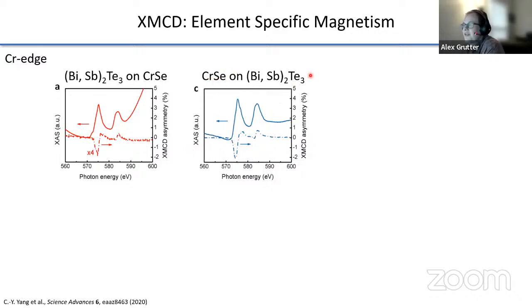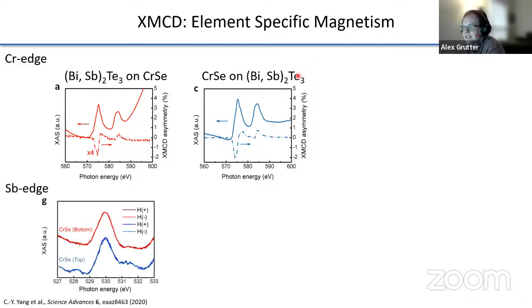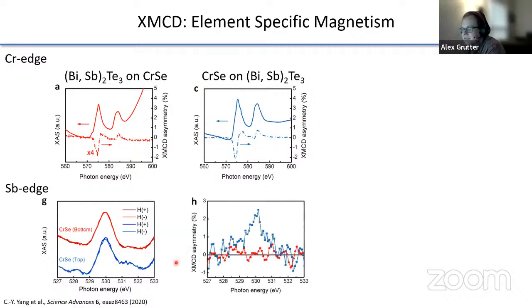And if we try to probe the magnetic state of the topological insulator at the antimony edge, what we see is that there's no splitting at all in this case here. And there's a very, very small splitting in this case here where chromium selenide is on top. And so this tells us that we have an actual net spin polarization that is being induced only in the case of chromium selenide on top of bismuth antimony telluride.